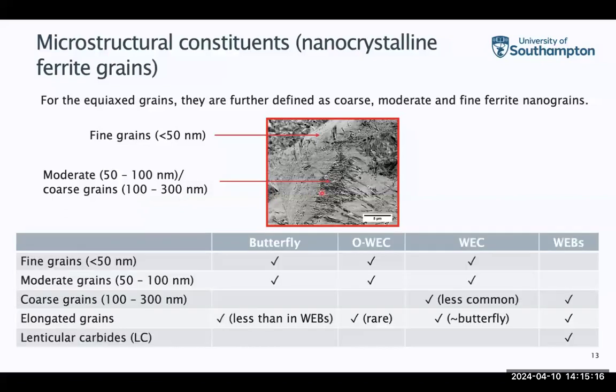So to summarize, for the four features, butterfly, oriented white-etching cracks, white-etching cracks, and the white-etching bands, we found that butterfly, oriented white-etching cracks and white-etching cracks all have fine grains, which appear to be very white, and most of them have moderate grains, which can be white or slightly darker, depending on what you have on the surface. The white-etching cracks also have some coarse grains, which is less common, so they're not the most.